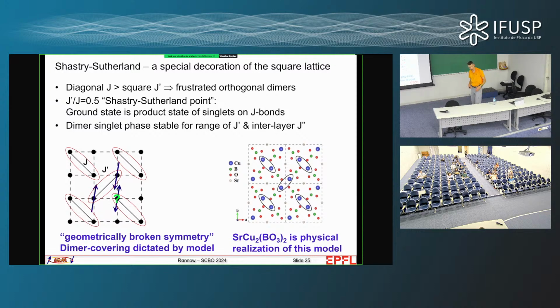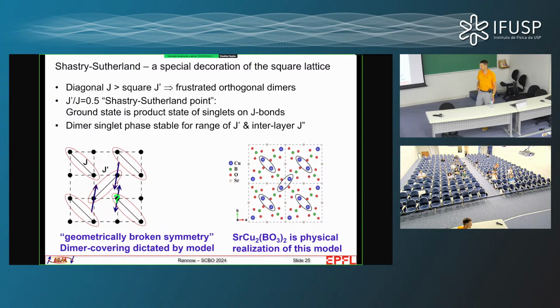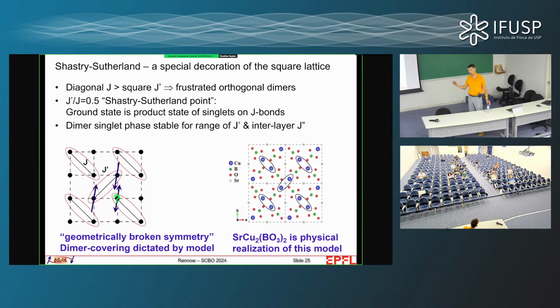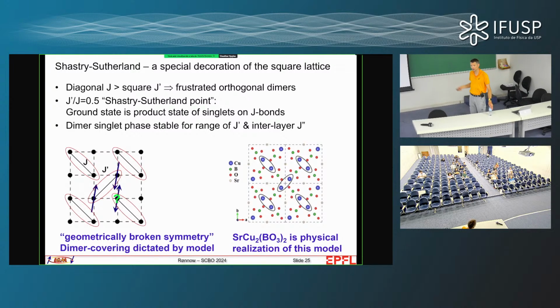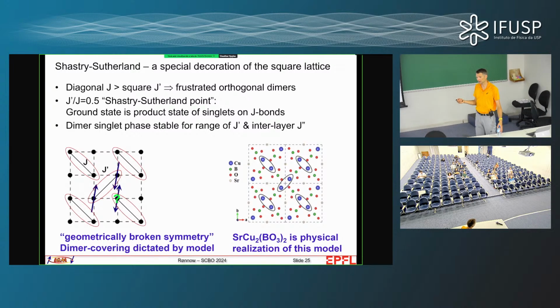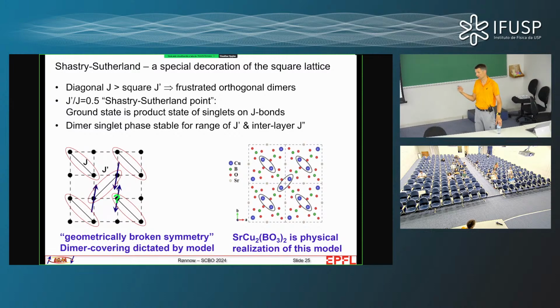And I have been looking through crystal structure databases, we've even tried to synthesize a couple of them, but we have not been successful so far. There exist some rare earth borates, which do have this crystal structure, but the rare earth ion has a larger moment, and it gets a crystal field, which means that it becomes anisotropic. And a lot of these delicate many-body quantum properties require a continuous symmetry, the so-called Heisenberg model.